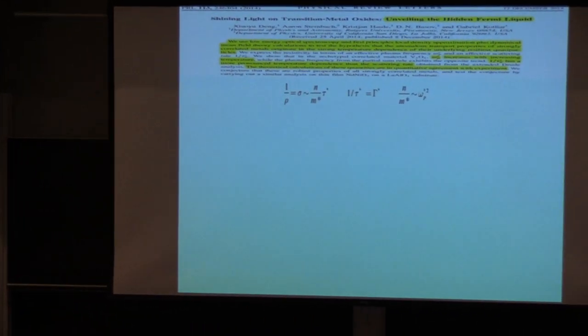Now, I would like to show you what we can do 10 years afterwards with the modern methods. And this is taken from a paper that we published in the last year, where we actually made an even more interesting prediction to the experimentalist. We were trying now to understand not just all the high frequency optics, but the DC resistivity. And you all know that through the formula that the conductivity has a tau and has an m. And what we said is that the way that these materials behave is such that if we look at the tau star, this will behave like a Fermi liquid. But the reason why the resistivity looks so strange is because the m star is a strong function of temperature. That's why we called it a hidden Fermi liquid, because from the point of view of tau star, it looks like Fermi liquid, but from the point of view of the resistivity, it is not.